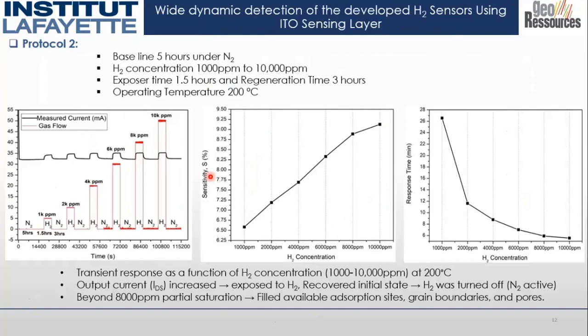Now we know the operating temperature of our sensor. For the second experiment, we fixed the operating temperature to 200 degrees and varied the concentration from 1000 ppm to 10,000 ppm. At the very beginning of the test, the sensor was kept under nitrogen for 5 hours for a stable baseline. Then we exposed it to 1000 ppm of hydrogen for 1.5 hours and gave 3 hours to regenerate the sensor. This way, we incremented our concentration from 1000 ppm to 10,000 ppm. The output current increased with the exposure to H2 concentration and recovered to the initial state when H2 was turned off.